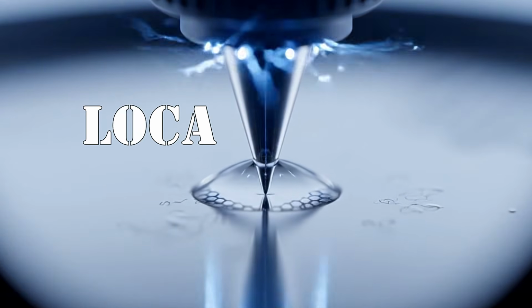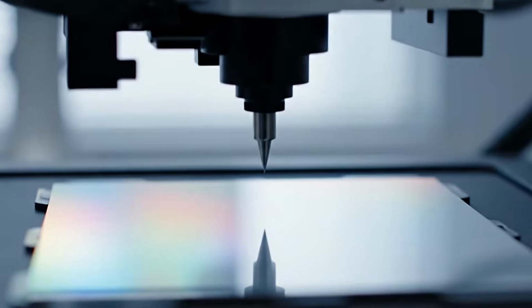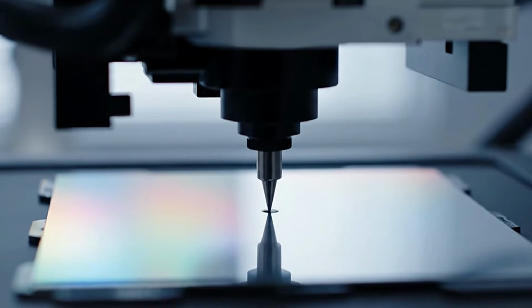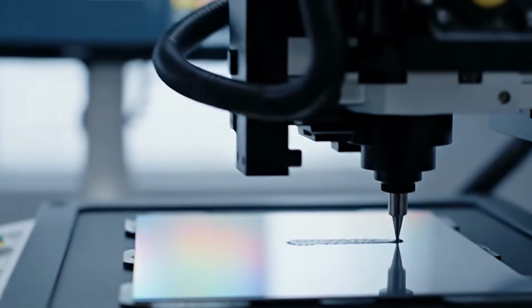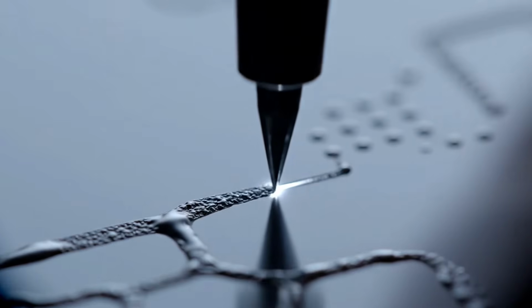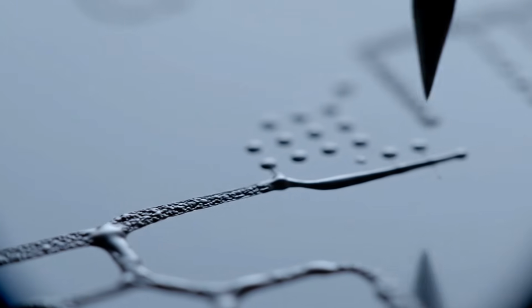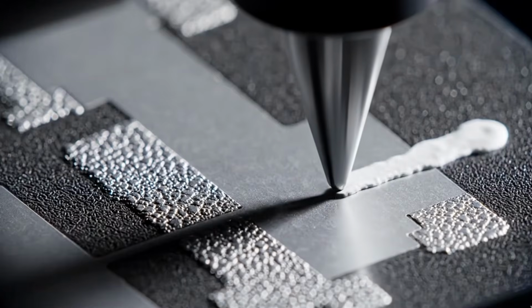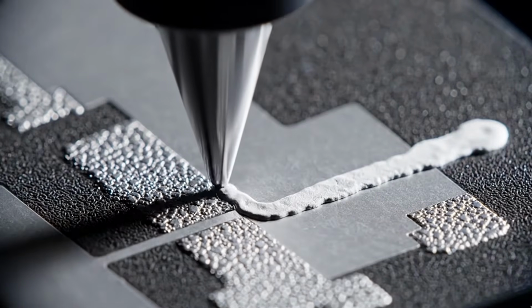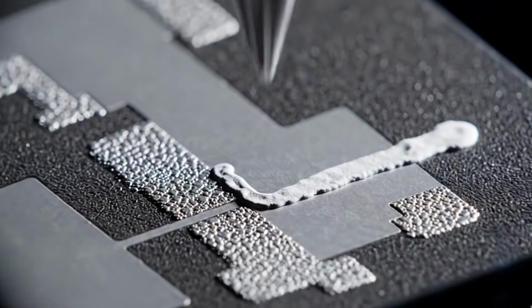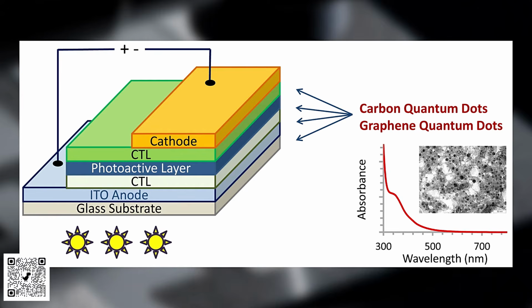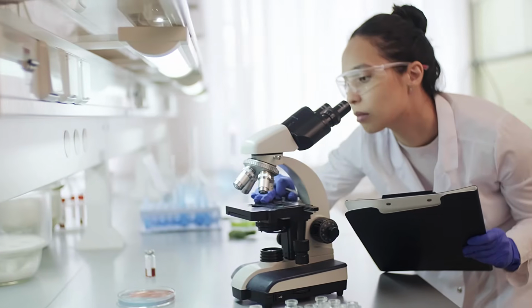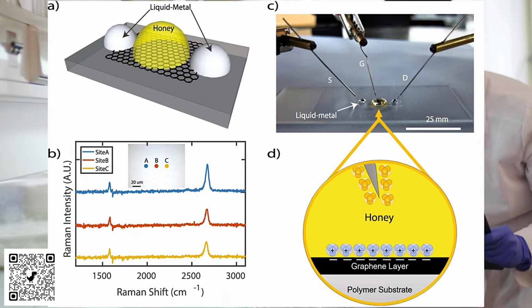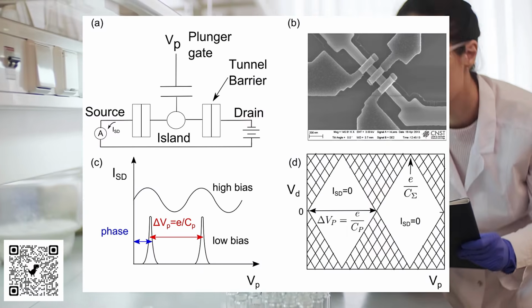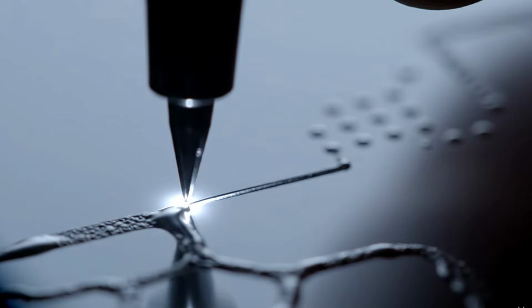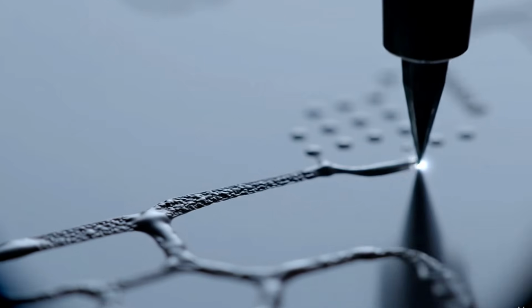Using a technique called local anodic oxidation, researchers bring the sharp tip of an atomic force microscope just nanometers above a surface like silicon, graphene, or titanium. A tiny water bridge forms, voltage is applied, and a nanoscale patch of oxide grows right under the tip. Line by line, you can ink insulating oxide patterns only a few nanometers wide, effectively writing resistors, tunnel barriers, or quantum dots directly into a device. Teams have used this to define nanotransistors in graphene, tailor memristor behavior, or confine electrons in single-electron devices. It's anodizing transformed into a nanoscale pen for electronics.